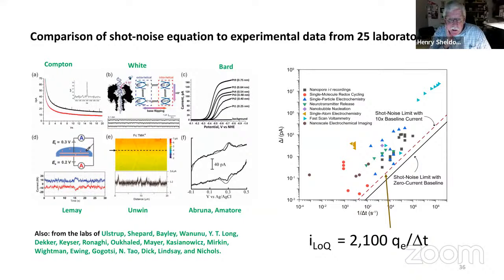There's actually an experiment I'm going to talk about, the nucleation experiment. The student doing this, Nick Beatty, measures the current response for ferrocene oxidation before, during, and after these measurements to make sure there's no change in the structure of the electrode. But frequently, and for reasons I can't explain, I don't have a really good answer for, when you're working with such small electrodes, all of a sudden there is a big change in the behavior in the current. So some restructuring of the 10 nanometer size electrode has occurred.